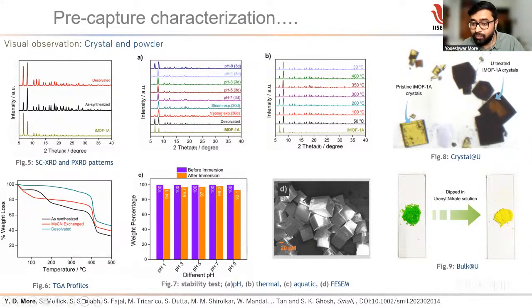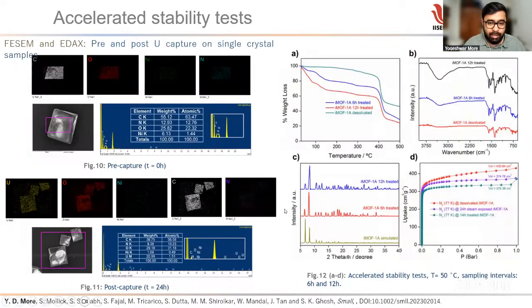Now, what we need to see is whether, if we treat it in water or any other solvents, the uranium is retained in the MOF so that it can be extracted at a later stage. That we are going to analyze. After doing the same on the MOF in the uranium crystal, we found that uranium is not only on the surface, but also within the cracks. So we took such a dried, uranium-exchanged crystal and broke it.